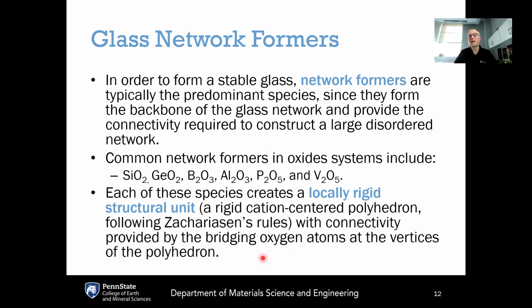And so if you have a glass that has multiple components, maybe you've got a boro-aluminosilicate glass that has boron units, alumina units, and silica units. Each one of these oxides has its own locally rigid structural unit. The silica tetrahedron, the B2O3 triangular unit, the alumina tetrahedra, and all of these units come together to form the boro-aluminosilicate glass by sharing corners with each other. So the tetrahedra and the triangular units will share corners with each other.